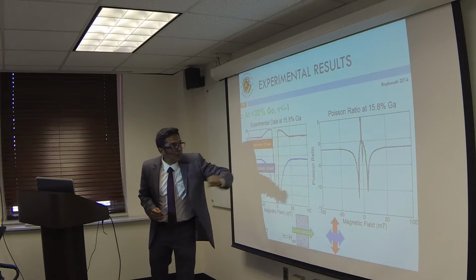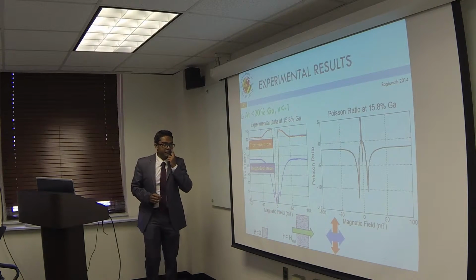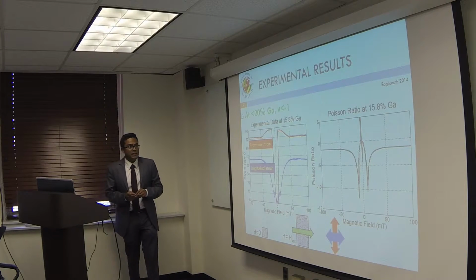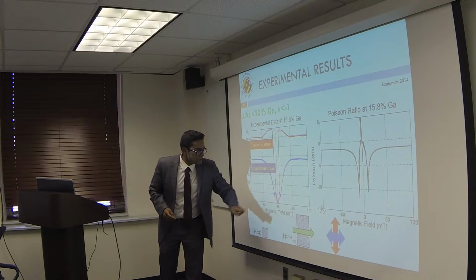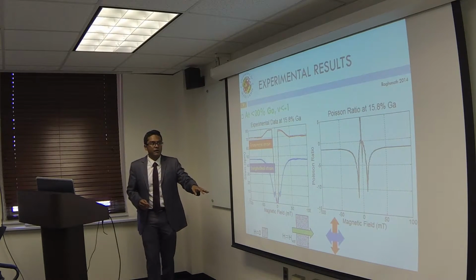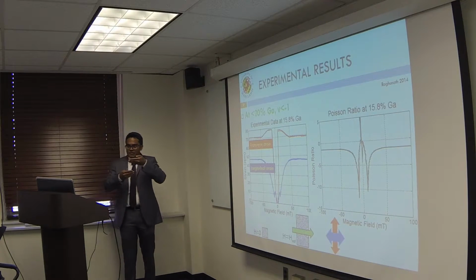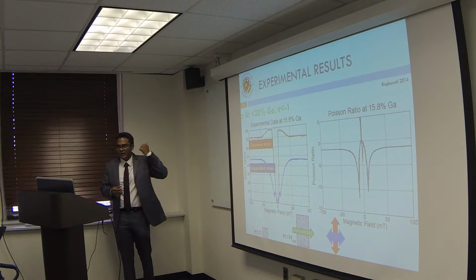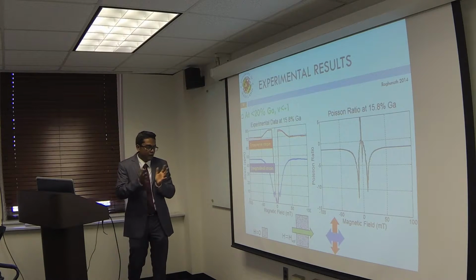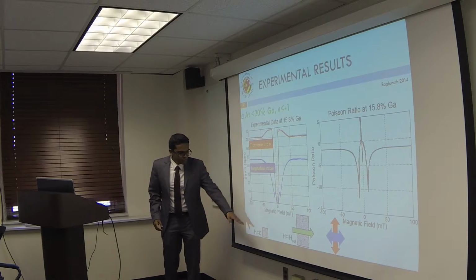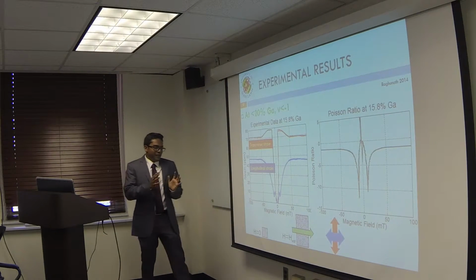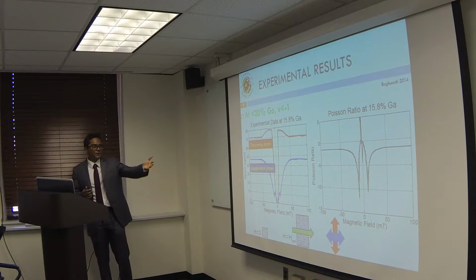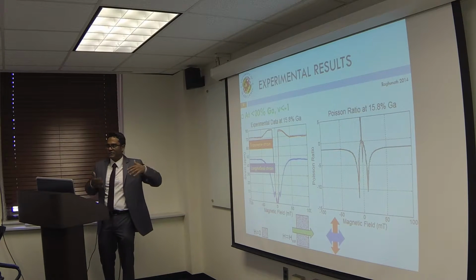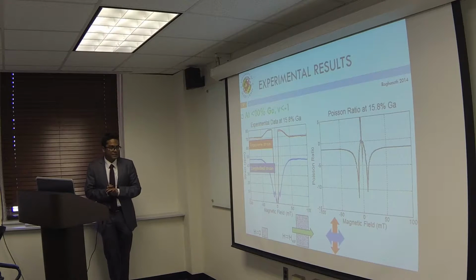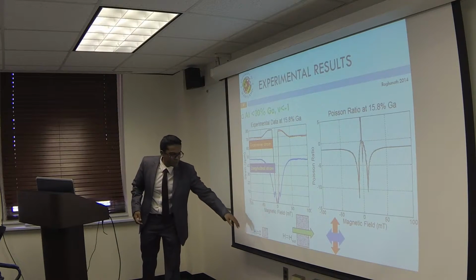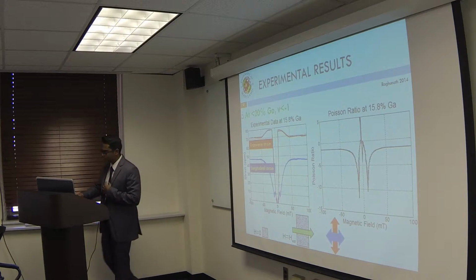The chart on the right shows the variation of Poisson's ratio with applied magnetic field. At really low values of applied magnetic field, you see some spikes because it's dividing one small value by another small value, which spikes up the value of the ratio. And this is just a cartoon that shows that there is a larger strain along the transverse direction than the longitudinal direction. So this is when there is a high magnetic field applied, and that's when we reach magnetic saturation.